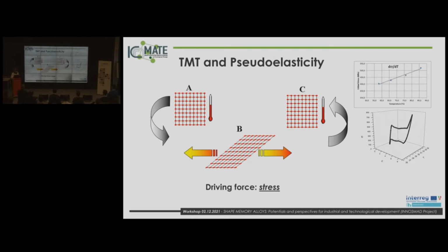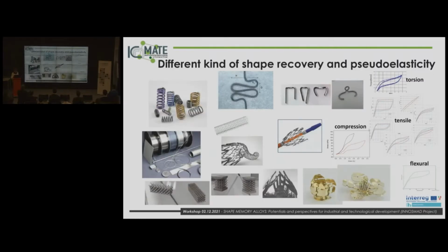Starting from these particular properties, we can consider how we can use the shape memory effect and the pseudoelastic effect of this material. We can use this effect in any shape we want. We can use wire, ribbon, spring, snake-like spring. We can prepare the material in very different ways. In this case, we also present some examples obtained by selective laser melting, for example, and we can modulate the response of the material in shape memory effect or also in pseudoelastic effect.